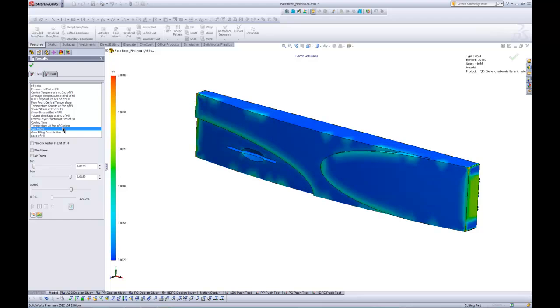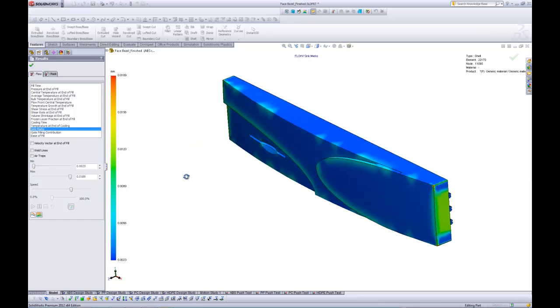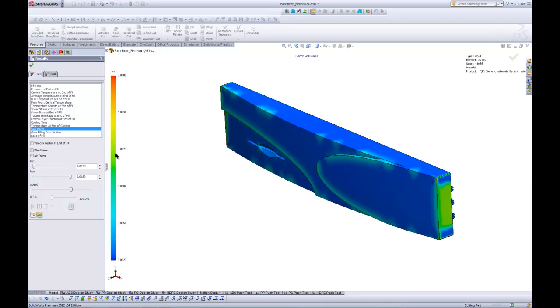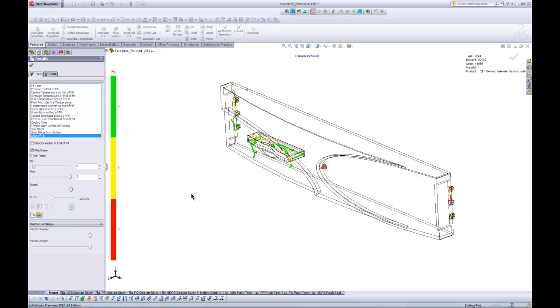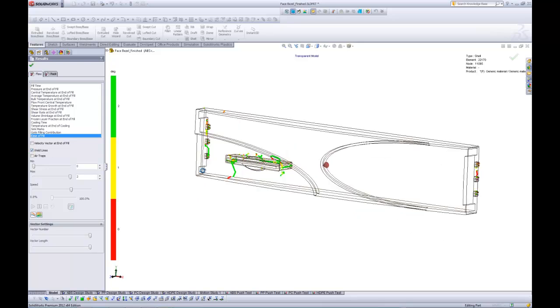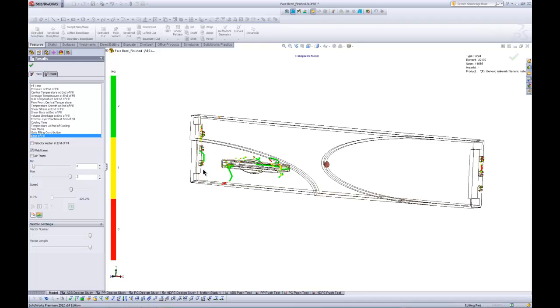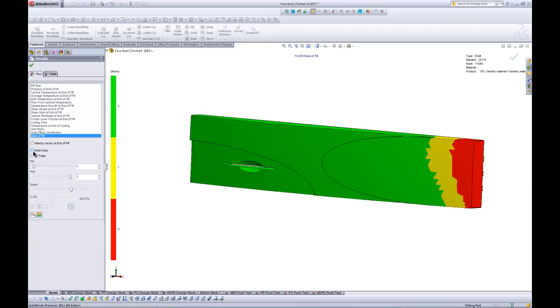We can look at things like sink marks. Take a look at exactly where the sink marks are going to be, the depth of the sink marks. We can look at ease of fill, which tells us areas that are going to require more than 70% of the injection pressure of the machine is going to show up in yellow and more than 90% or 85% is going to show up in red. We can also look at weld lines. So weld lines are basically places where the flow fronts come together and hit and they can be areas where you're going to have low strength. Also on plastic injection molded parts, they could be areas that you're going to have some visual discoloration. So you wouldn't want your weld lines to be places on cosmetic parts that people are going to be looking at.